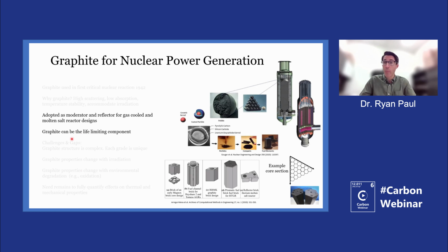Different designs adopted by different countries and different time periods have kept in some designs graphite as a moderator and reflector material for both gas-cooled and molten salt reactor designs. One very important part of this is that graphite can often be considered the life-limiting component of the design, such that the degradation of the graphite by irradiation or by other mechanisms could be the reason why the graphite has to be refreshed or there has to be a shutdown. And so there are different forms of graphite bricks and blocks that have been used in different designs, highlighted here, and used in various arrays in the overall reactor design.